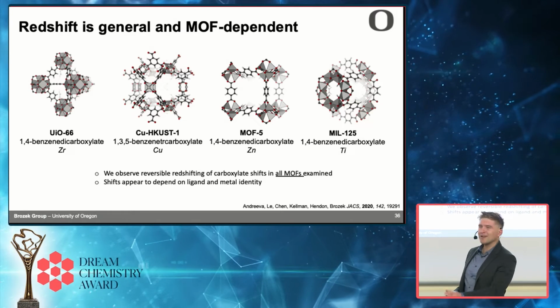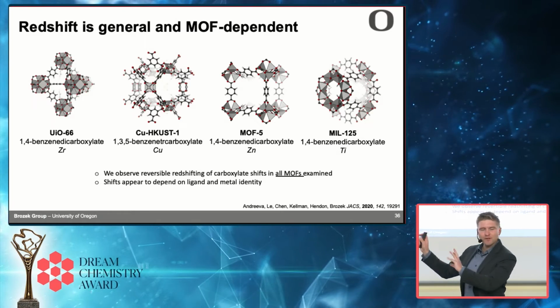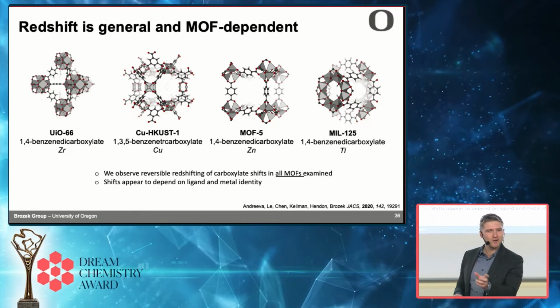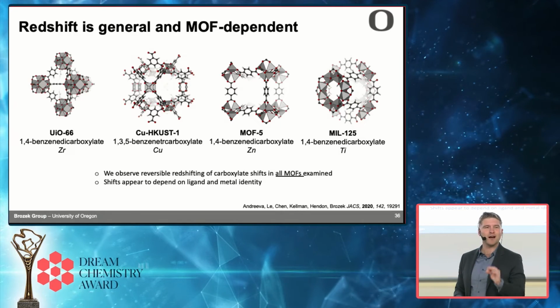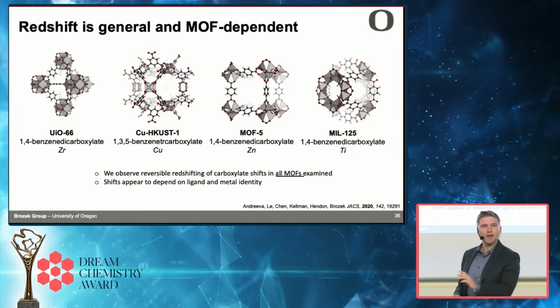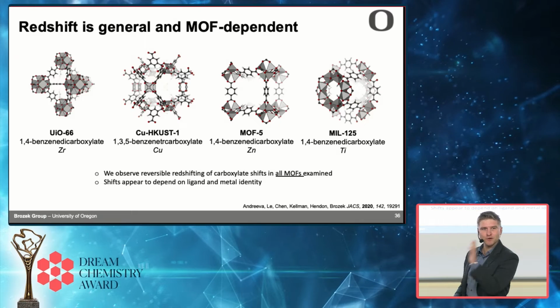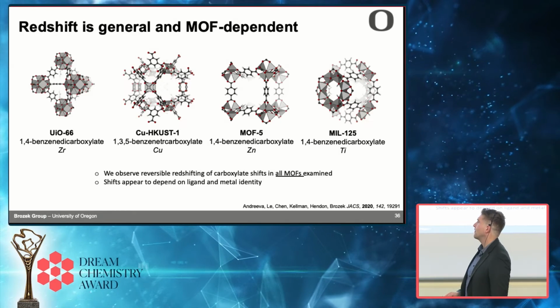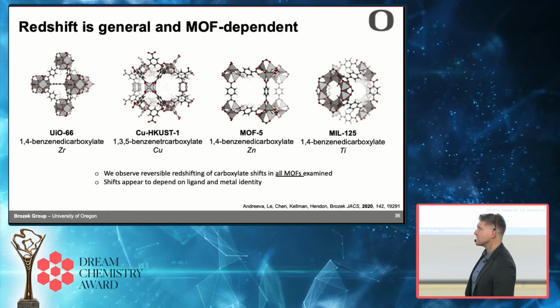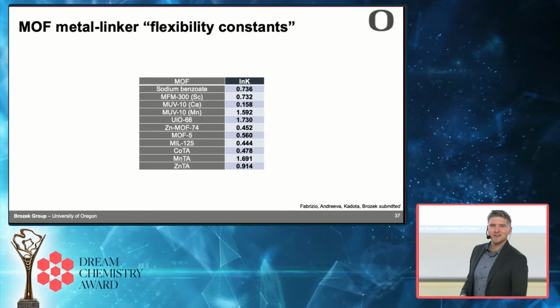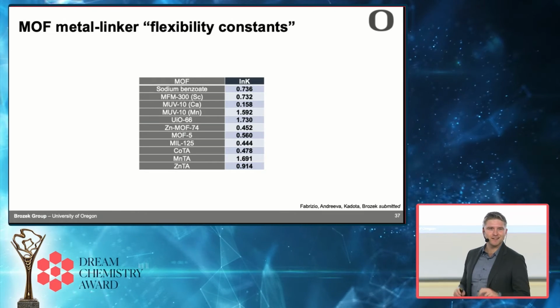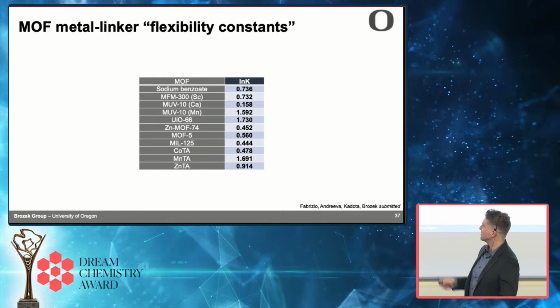And we did this with all these different common MOFs. So they all have different metal carboxylate geometries, so the IR spectra, they all look a little different, but the thing they all have in common is you heat these MOFs up, and the carboxylate stretches redshift reversibly. They all do the same thing. And we can perform the same analysis with all of them. And so we call this the flexibility constant. It's not the same thing as the stability constant, the flexibility constant.